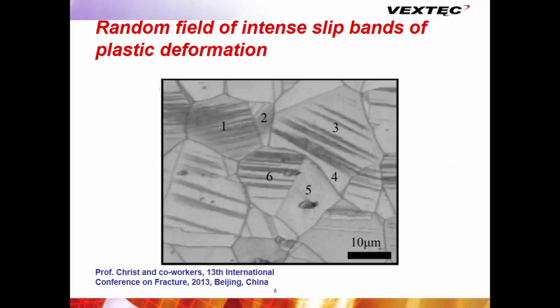Here's an example. I believe this is a nickel alloy, but again, very early in life, before I've got a crack, things go on such as very high strains in very, very small slip bands. So I've got a total strain, but that total strain is accommodated not by a little bit of strain everywhere, but by a whole bunch of strain in a really small place. We all understand how intense slip drives things, and those slip bands tend to stop at grain boundaries.